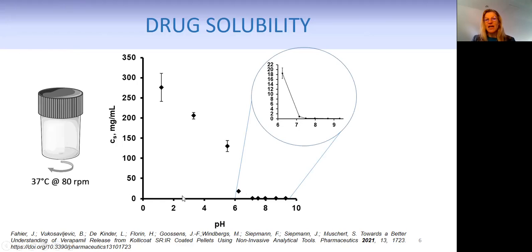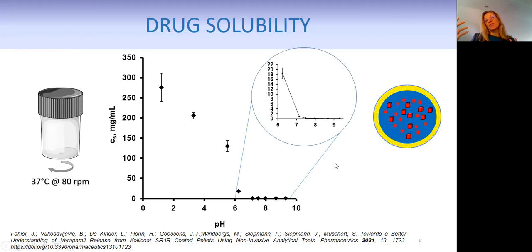So this explains why for acetate buffer, we've got a higher drug release compared to phosphate buffer 7.4, because in acetate buffer, we have got more of the dissolved drug, which is represented here with the little stars. Only the dissolved drug is able to diffuse through the coating out of the device. And in pH 7.4, we've got rather crystalline drug. Crystalline drug, represented with these little cubes, is not able to migrate out of the device.